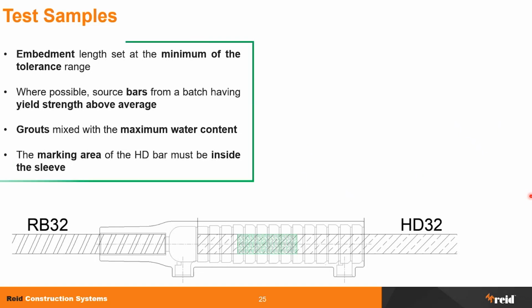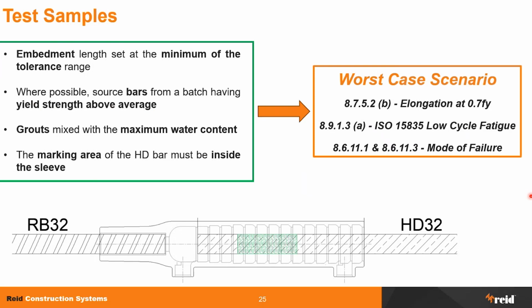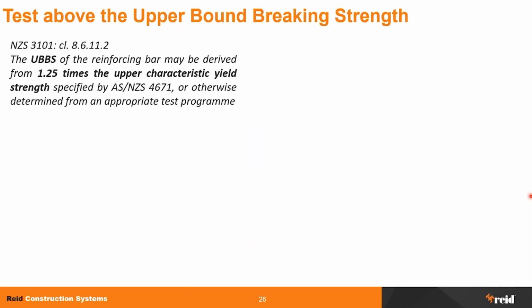And therefore, with all these, we ensured that we were testing the worst case scenario for the elongation at 0.7 fy for the low cycle fatigue, and also to demonstrate the mode of failure of the mechanical splice, where we want to achieve the ductile failure of the bar, clear of the coupler. Now, there is another requirement which is unique to New Zealand, and is to the capacity of this coupling system to develop the upper bound breaking strength of the bar.